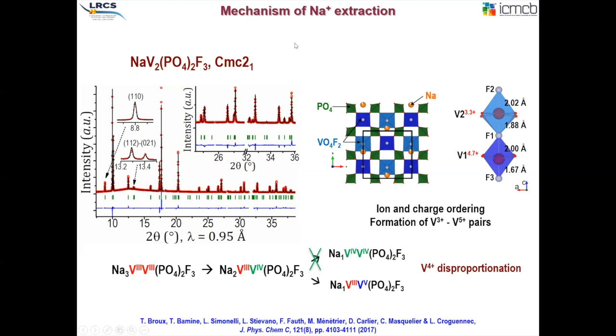Very interestingly, we determined from the X-ray diffraction analysis, plus also from X-ray absorption analysis, that we don't have a single vanadium 4 plus on the crystallographic site, but we have vanadium 3 plus and vanadium 5 plus coexisting in the same powder, in the same material, with these two octahedra that share a corner, the fluorine corner. So this is some sort of so-called disproportionation, and we were able to identify it for this compound.